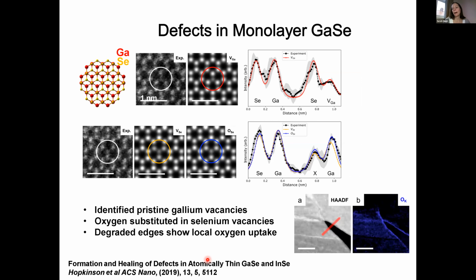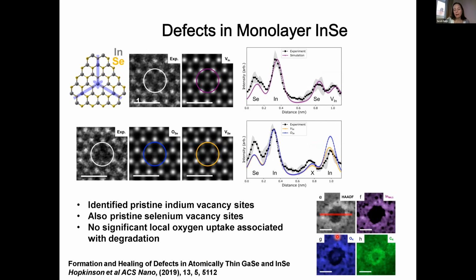This is for the monolayer gallium selenide. Here we see vacancies both in the metal sites and the chalcogen sites. In gallium selenide, the selenium sites have been substituted by oxygen, and we also see oxygen uptake for regions of degraded structure. Similarly, in indium selenide, we see both metal and chalcogen vacancies, but here we don't see the selenium being replaced by oxygen. And that's reflected in the same when we do low magnification elemental mapping. We don't get oxygen uptake in the degraded regions.